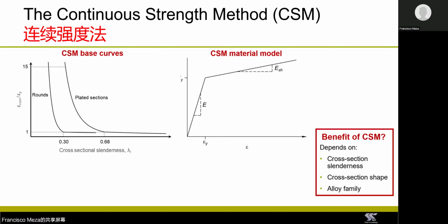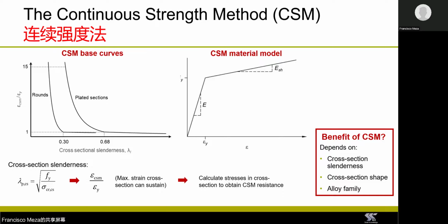So the way the continuous strength method works is, first, you have to calculate the slenderness of the cross-section, which is given by the square root of the ratio between the yield strength and the elastic critical local buckling stress of the cross-section. Then you can use what we call the CSM base curves, which give you the maximum compressive strain the cross-section can sustain before failing due to local buckling. And once you know the maximum strain the cross-section can sustain, you can use the CSM material model to convert the strains within the cross-section into stresses. And once you know the stresses within the cross-section, you can determine the resistance of the cross-section by integrating the stresses over the cross-section. Now, you don't need to do any derivation in order to use the CSM. Eurocode 3, Part 1-4 will give you all the equations that you need to calculate the CSM resistance.